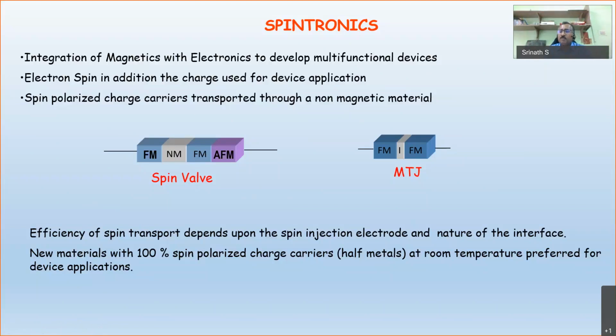That gives me a device. It's called a spin valve. So now you see that earlier I could have controlled the flow of these charge carriers based on temperature, defects, and whatever scattering mechanisms are involved. But now I have additional control based on the spin of the electron, which I am changing at my will, up and down, by the application of a magnetic field or through spin orbit coupling by an electric field, without affecting this flow. So I can make the flow of electrons across this non-magnetic spacer either on or off. This non-magnetic layer normally is a metal.